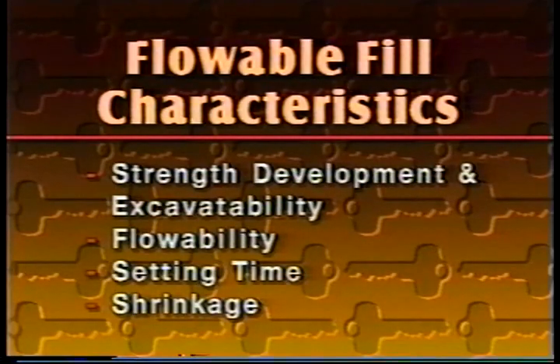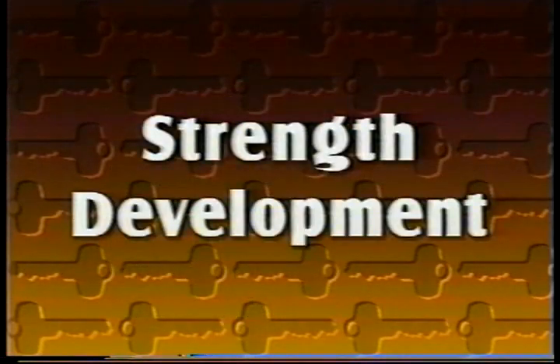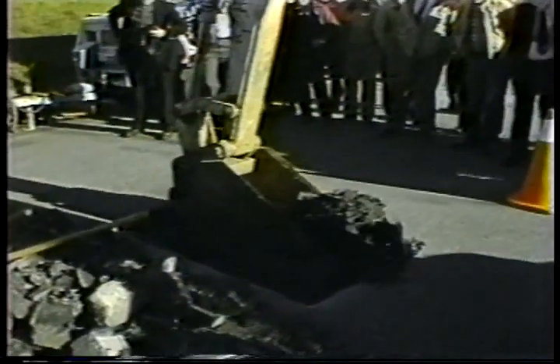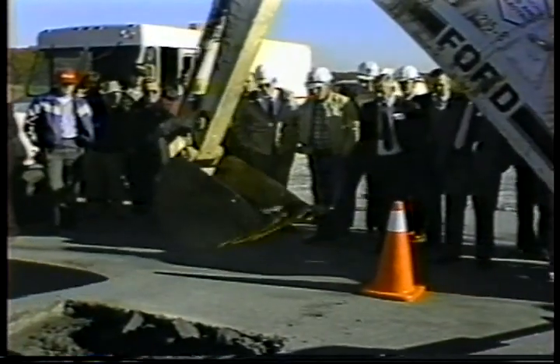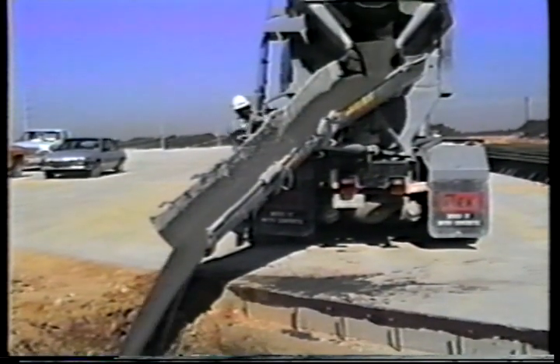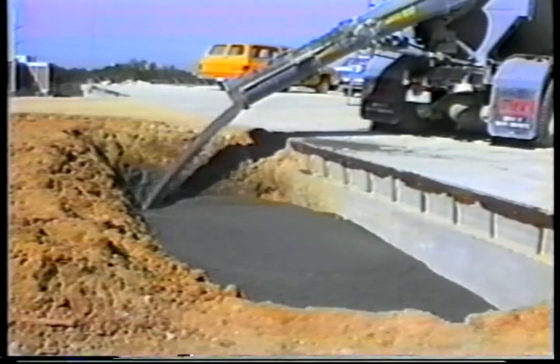The four most important physical characteristics of flowable fill mixtures are strength development and excavatability, flowability, setting time, and shrinkage. Flowable fill with a compressive strength of 50 PSI or less can be excavated manually. Mixtures with compressive strengths of 100 to 200 PSI may be excavated with mechanical equipment. Applications not requiring future excavation, such as bridge abutment backfill, may require higher strengths.